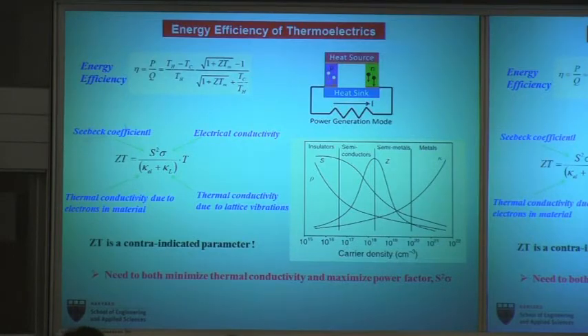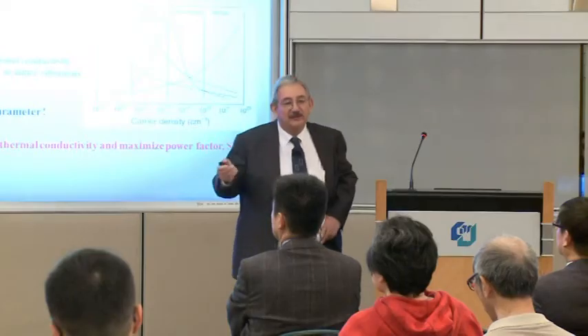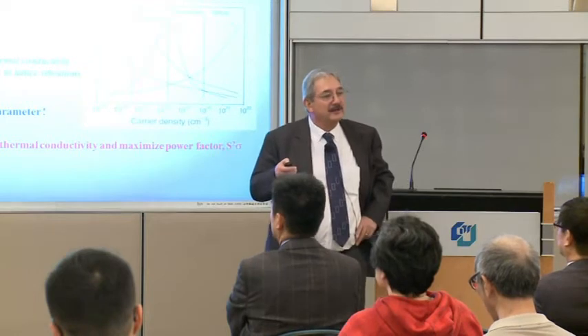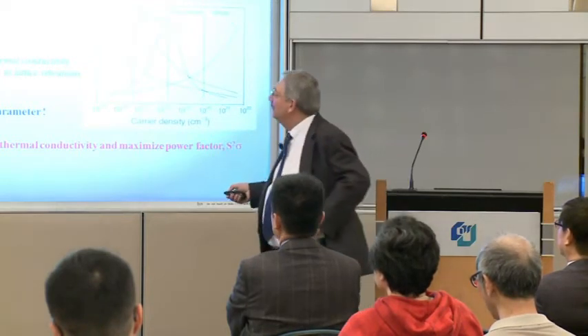And so this is just a rather standard plot. And it shows that for a standard type of semiconductor, as you increase the number of electrons, the Seebeck coefficient decreases. Remember, you need this squared, so that's important. At the same time, the thermal conductivity goes up. That's because of this electronic contribution. And lastly, of course, the resistivity goes down. So there's an optimum value for, in this case, carrier concentration in order to maximize ZT.